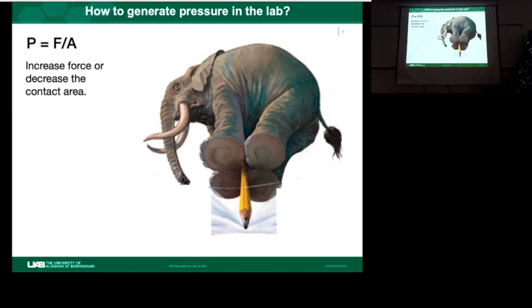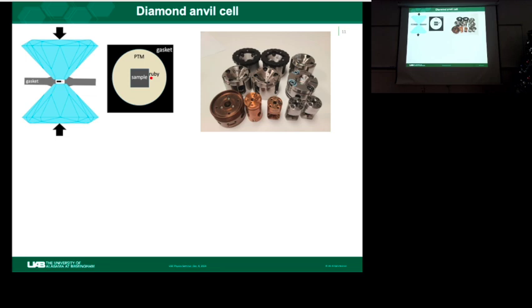Okay, so I mentioned that we use a diamond cell to generate high pressure, and also other types of devices to generate high pressure in the lab. Basically, the trick is either you increase the load or you make the contact area smaller to achieve very high pressure. The basic components here are two opposing anvils, and you don't want the two anvils crushing on each other, so you typically have a metallic gasket with high strength going between the two diamonds and forming a sample chamber. So you load a piece of sample, and you also need to know how much the pressure is in the sample chamber. So we load a tiny piece of ruby on the scale of 5 micron to 10 micron.